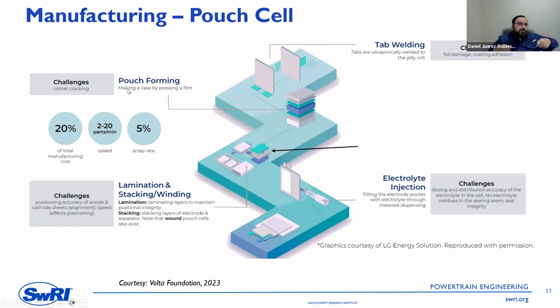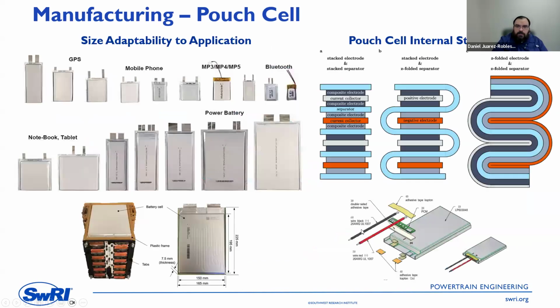The pouch is just a simple bag. It could be either a nylon or aluminum covered with some protective layer because the electrolyte, at least the liquid electrolyte, is highly corrosive. And then you can start forming the cell. Once that you cut the cell, you can put the electrodes inside of the cell and fill it with electrolyte.